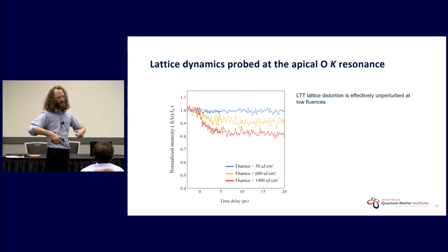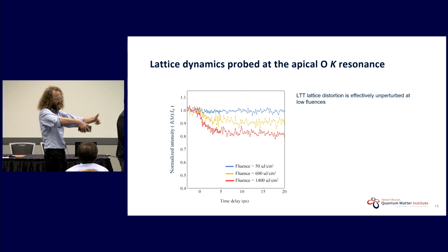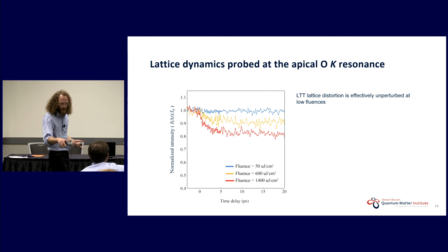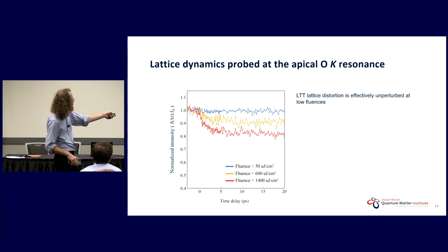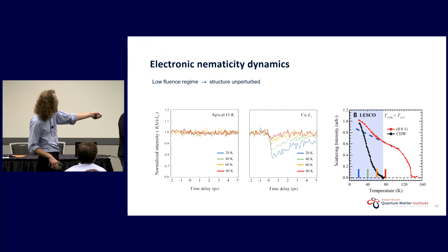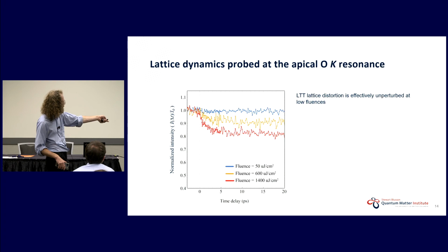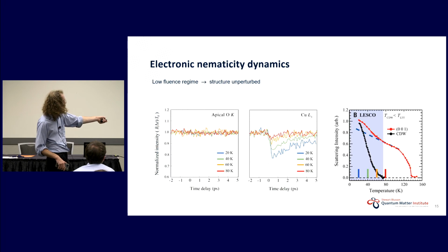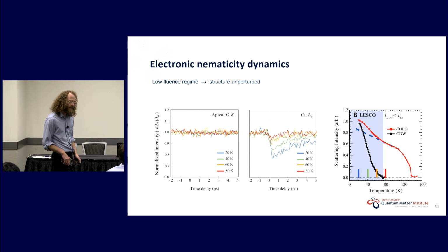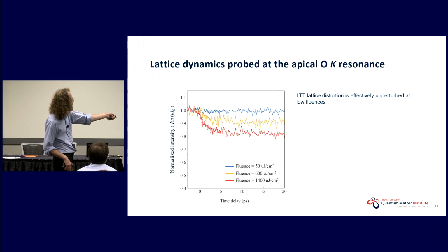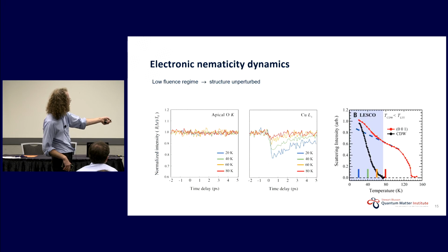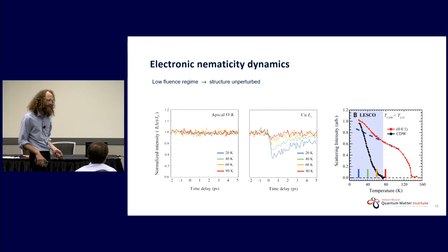That's how I'm understanding it. You've now excited all these lattice vibrations, and now they have to diffuse. But do I understand correctly that you're measuring the same peak at different energies, and it recovers with different time scales? So here's the trick. If I now pump at a high fluence, comparable to this, then I will also get overlaid on this electronic signal a lattice-type signal which doesn't recover and looks exactly the same. I'll get the superposition of the two. But at low fluences there is no lattice signal, so at the copper edge I'm superimposing no signal with just this electronic response. Does that answer the question?